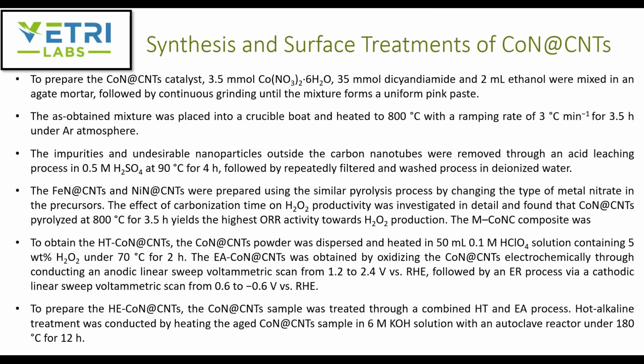So how they did the synthesis and surface treatment of these cobalt nitrogen doped carbon nanotubes. To prepare these cobalt nitrogen doped carbon nanotubes, they used 3.5 millimoles of cobalt nitrate salt and 35 millimoles of dicyandiamide to have the nitrogen doping, and 2 milliliters of ethanol in an agate mortar, mixed, and then they continuously ground it to form a thick paste.